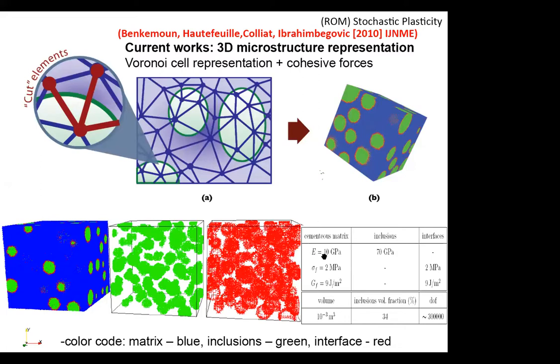And you can see that to prepare the data for such a model, we said that the inclusion, that means aggregates, is simply elastic. Typically, it took 70 gigapascal as the modulus of this inclusion. Then cement, you can be testing independently. Here we took a much smaller value, of course, for Young's modulus. It has a rupture at 2 megapascal. This is conditioning the traction resistance of concrete because you will see it breaks through cement. And secondly, the fracture energy of cement is taken to be 9 joule per square meter. Interface, we could go and we will go into very elaborate modeling with random fields, but initially we can just take it to be deterministic.